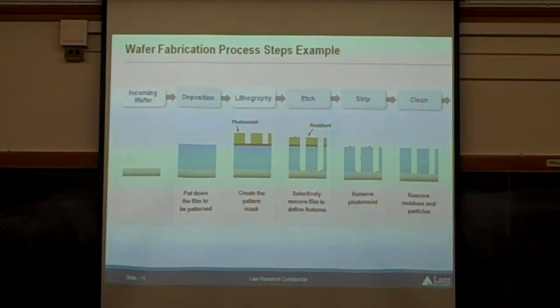Well, I actually use a photographic process, although it's on a very, very small wavelength scale, where you spin on this green layer, which is just a polymer essentially, but it's an optically sensitive polymer. And then I have a mask of what I want the pattern to look like on the wafer. I shine a light through of the right wavelength. In this case, it's a UV exposure, or a UV light source. It's blocked where the mask is opaque, and it transmits through. And where it transmits through, it'll cross-link. So I end up with a region where, when this polymer layer is on there, this is hard, this is soft, hard, soft.